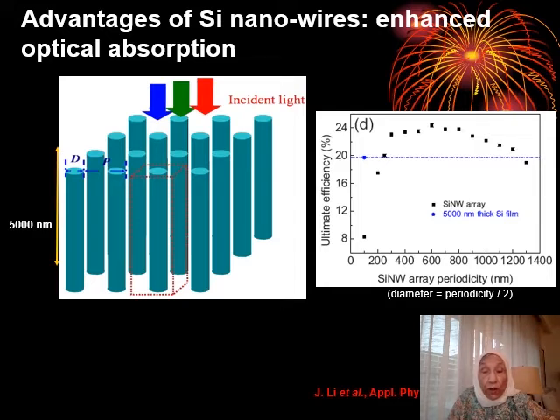And the curve for silicon nanowire array periodicity as a function of ultimate efficiency is seen on the right side, with an increase up to 24%. And in this case, the silicon film was 5,000 nanometer. The silicon array was clearly given in the black points. The efficiency is given in the black points. And it shows how the silicon nanowire array periodicity at the bottom varies from 200 nanometers to 1,400 nanometers.